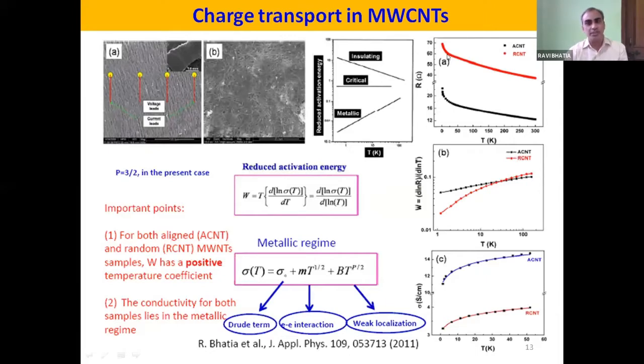At sufficiently low temperature, for example, 1.4 to 10 Kelvin, there is a little rapid enhancement in the resistance, which occurs because of the constructive interference of the partial electron waves. And when this particular constructive interference is broken or destroyed by either magnetic field or temperature, it shows positive MC and negative MR. I would just try to explain how it is metallic.